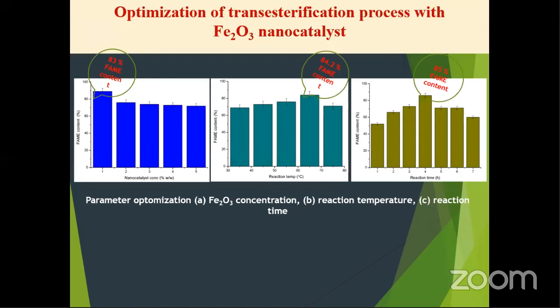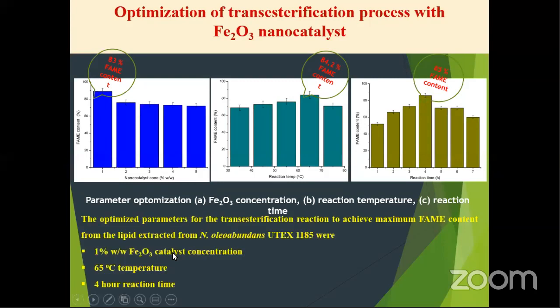successful synthesis of the nanocatalyst and the preliminary study, we have to optimize the transesterification process parameters using this Fe2O3 nanocatalyst. So first we have to optimize the concentration of the nanocatalyst in the solvent mixture used for the transesterification reaction. So the nanocatalyst concentration varied in the range of 1 to 5% was considered, and it was found out that for the case of 1% weight by weight nanocatalyst concentration, the FAME content, that is biodiesel yield, is 83%,